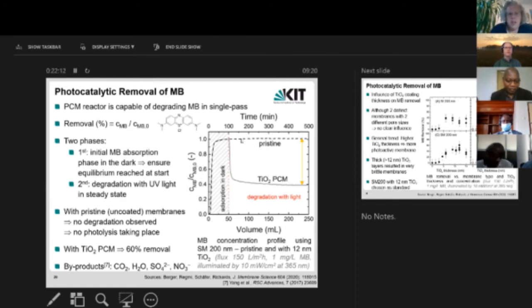But what I'd also like to highlight here is the dotted top curve. The dotted top curve is the pristine membrane only, with no titanium dioxide present. And the fact that there's no removal here indicates strongly to us that there is no photolysis reaction of the methylene blue. Thus, the methylene blue here is only being destroyed in the presence of the titanium dioxide.